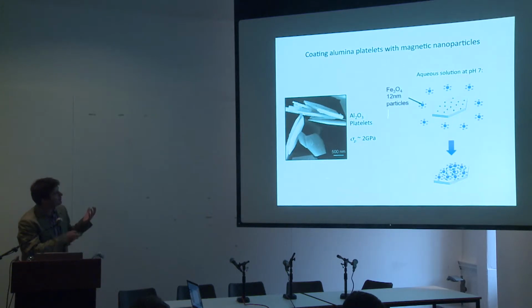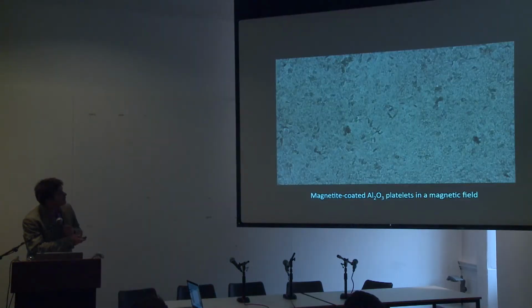So this is how we do it in practice. This is one of the types of reinforcements we use. These are ceramic, very stiff platelets of aluminum oxide, about 10 micrometers in the long axis and 300 nanometers in thickness. And now we coat them with iron oxide nanoparticles, so basically rust nanoparticles. So now I'm going to do the same experiment I did at the macroscopic level, but now under a microscope, looking at each one of these tiny microplatelets with the iron oxide coating. So first, they're relatively heavy. They're 10 microns, and aluminum oxide is quite dense.